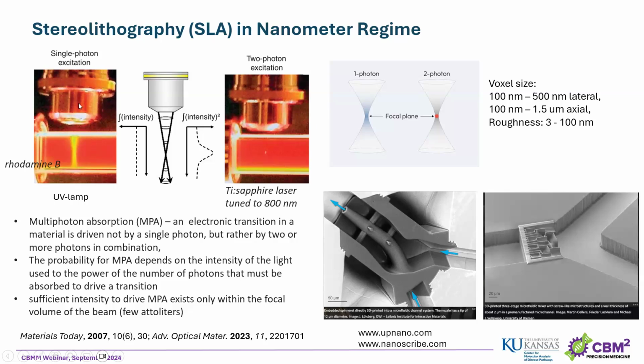the beam from the microscope objective through the solution of rhodamine B, you can see how wide this beam is in the rhodamine. So how much of this rhodamine B is excited to give off fluorescence, right? Versus if you run it with a titanium sapphire laser at 800 nanometers in this two-photon mode, you can see that this really, really tiny area at the tip is excited.